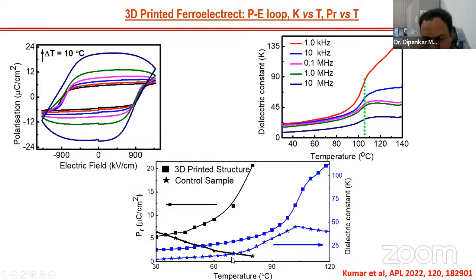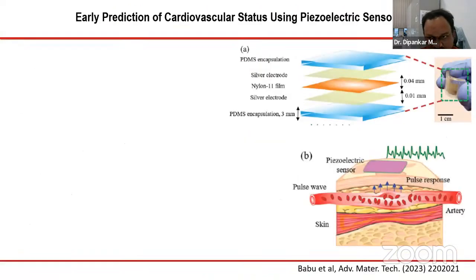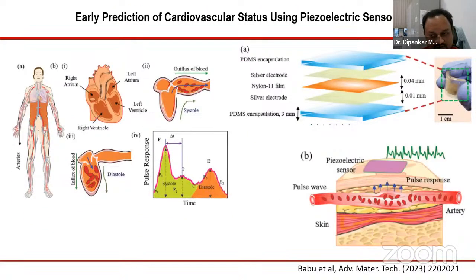Similarly, in the dielectric constant, in the case of normal piezoelectric or ferroelectric materials, at Curie transition temperature, after Curie transition temperature, it declines. So it gets decreased. However, in the case of ferroelectret materials, you see the dielectric constant is increased. So now I will take 5 minutes just to show you some example.